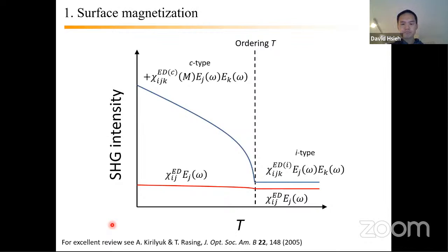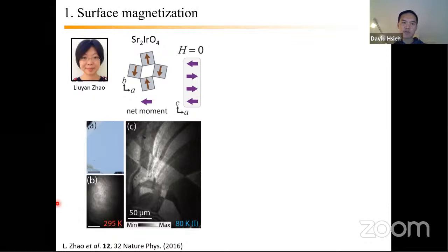Okay, but I want to just use a recent experiment from my group to illustrate what you might expect from a surface response. One of the compounds we've been working on a lot is strontium iridate, which is sort of this strongly spin orbit coupled cousin of lanthanum cuprate, lanthanum 2 copper O4. And in this compound, you also have this two sublattice Néel order, but there's a canting of the oxygen octahedra that results in a net magnetic moment per layer, okay?